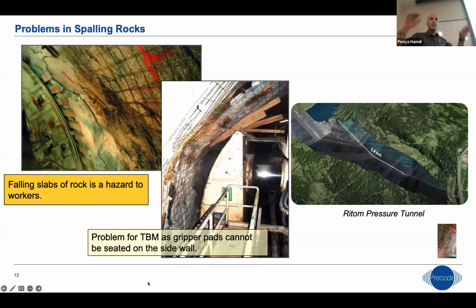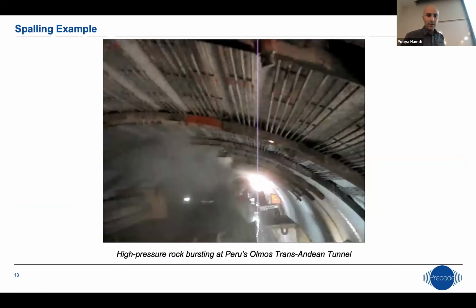What was happening was that the spalling was developing around the tunnel, and the TBM was going 45 to 60 degrees upward. All of a sudden you have a wall that is not sustaining any load anymore. In a normal horizontal tunnel, it's not a big deal; we can hopefully go with it. But when you have a TBM going 45 to 60 degrees upward, gravity is not really helping. So if you have spalling, you're going to have really big problems. What they did here was put in a lot of cable bolts and wire mesh as soon as the excavation was done, to prevent this spalling from developing.